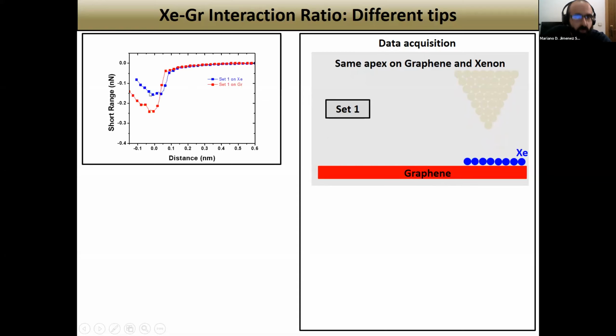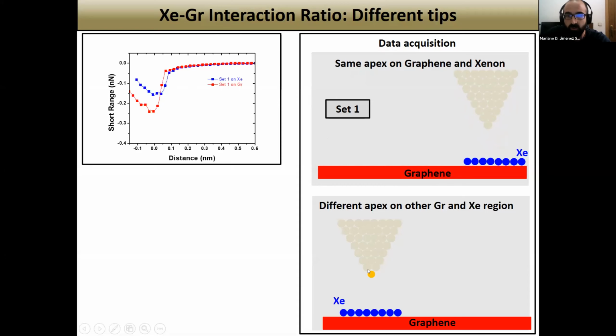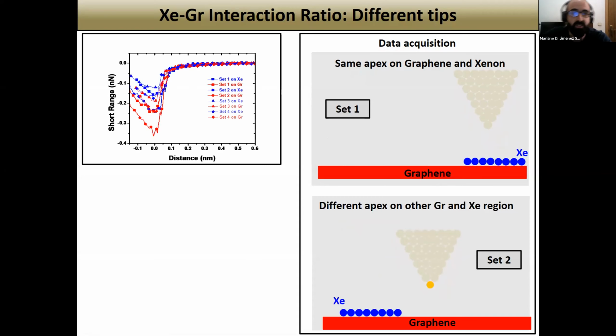that I show you here. The blue curve has been acquired on xenon and the red on graphene. We have repeated this process with another tip apex on another region, and we have obtained a second set of data. We have repeated this process many times. Here I show you as an example four sets of data. And what we observe here is that we have a large short range dispersion as a consequence of the different tips that we have employed.